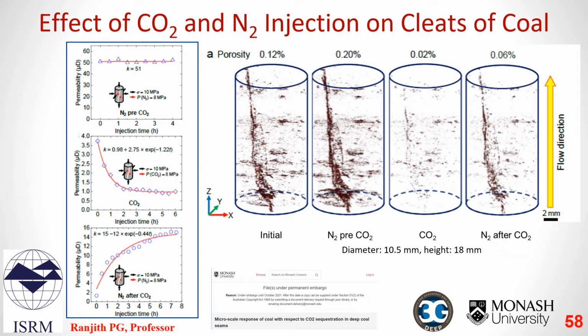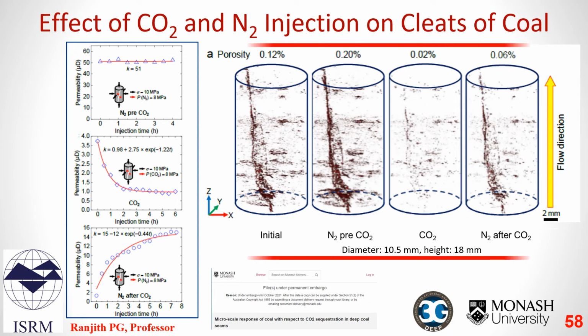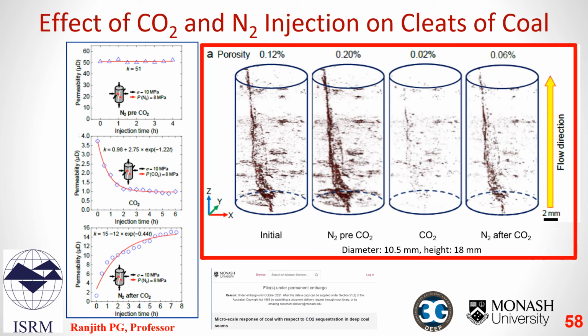In order to understand the cleat scale mechanisms, we conducted a series of co-flooding tests to indicate the permeability variation caused by injecting nitrogen, then carbon dioxide, and then again nitrogen, as you can see here in the experimental results. At the same time, we observed the cleat network changes in CT images at different injection stages.